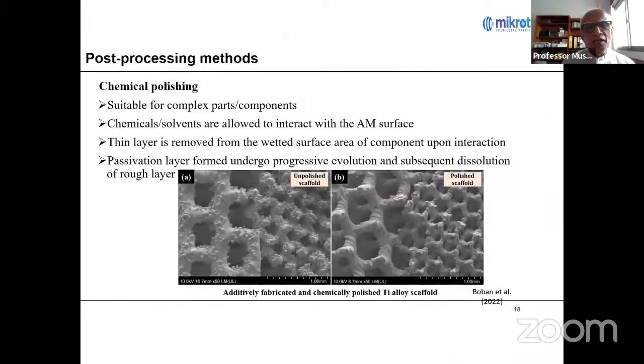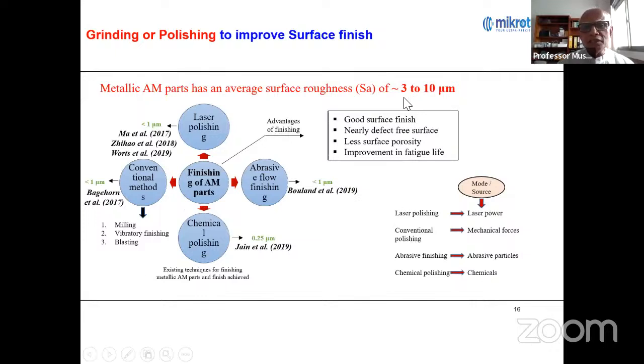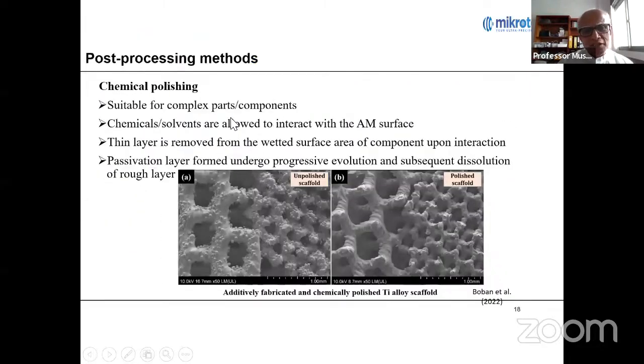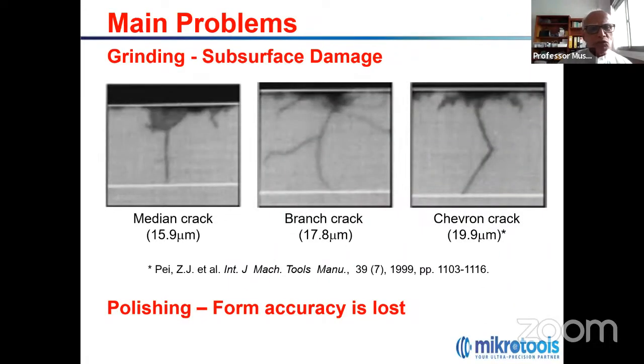One slide I missed. Actually, usually after 3D printing, you get a surface finish of 3 to 10 micron, and by different processes, they can reach up to 1 micron. But surface finish is somehow acceptable. But the main problem is when you do it by grinding, there are cracks of different dimensions. It could be a macro crack, it could be a nano crack, but there are cracks. As long as there is a crack, the surface is not perfect, and that cannot be considered a high precision, ultra precision part. So it cannot be used for high quality products, especially for optics.